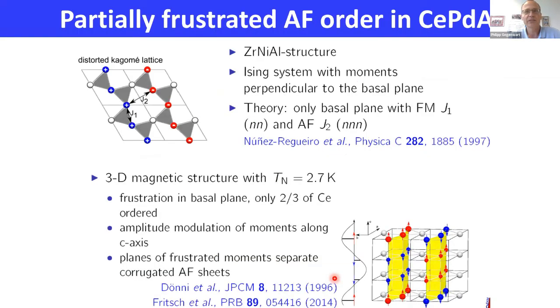And that's a motivation to look for Kondo lattice metals where the 4f electrons are located on frustrated lattices. This zirconium nickel aluminum structure type, with the perfect triangular units which are connected in a Kagome lattice, although it's distorted, has a frustrated nearest-neighbor coupling, and therefore there is a strong motivation to look for Kondo lattice systems of this structure type. And one of the prototype members of this family class is, of course, cerium palladium aluminum, which has been studied for